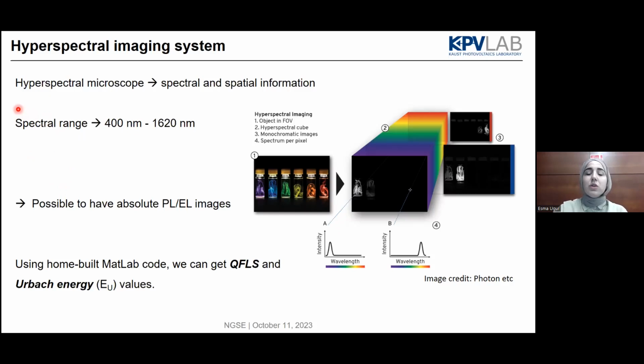Here, to get the image of the sample, a thin film on a surface, we are using a hyperspectral microscope. Basically, it gives both spectral and spatial information, because you are getting an image that has information from 400 nanometers up to more than 1600 nanometers, and also over an area.